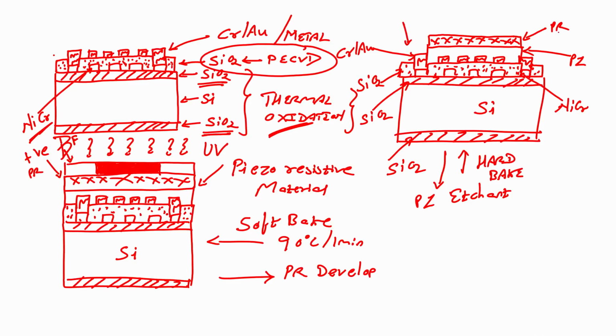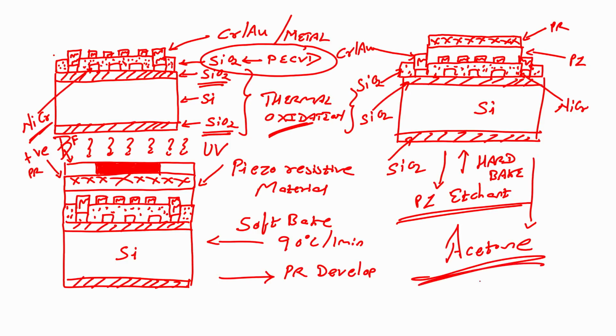in this region and this region. So, once I dip the wafer in a piezoresistive etchant, I will etch my piezoresistive material which is not protected by photoresist. Next step for this would be that I will dip this wafer in acetone. If I dip the wafer in acetone, what will happen? We will strip the photoresist.